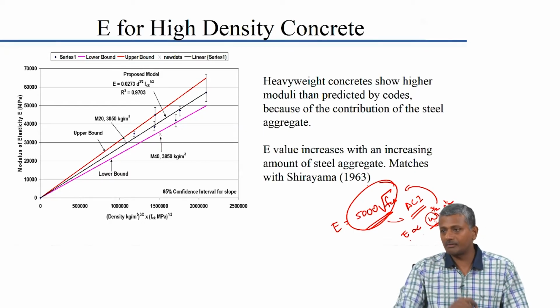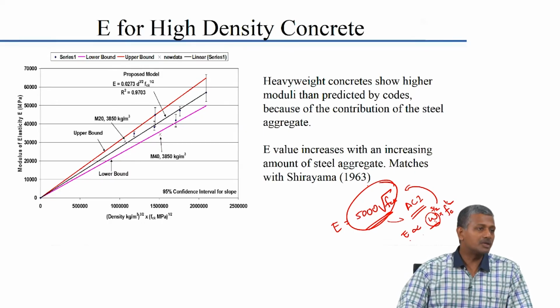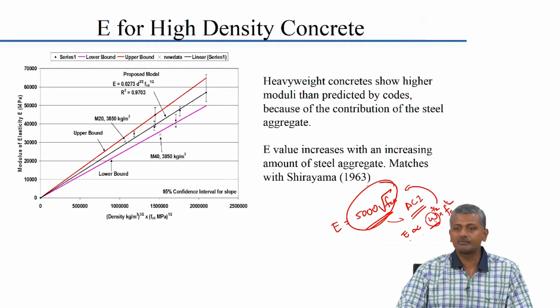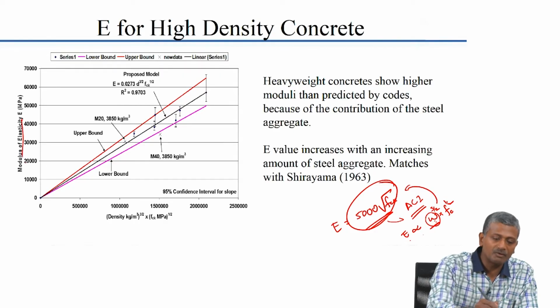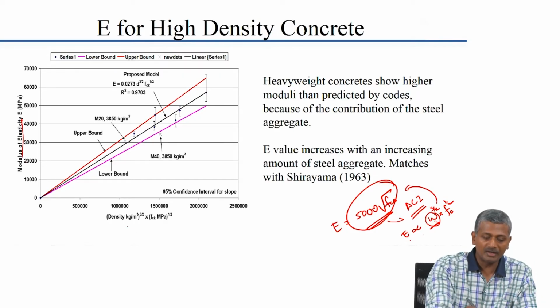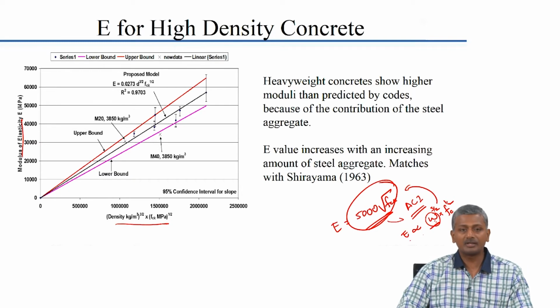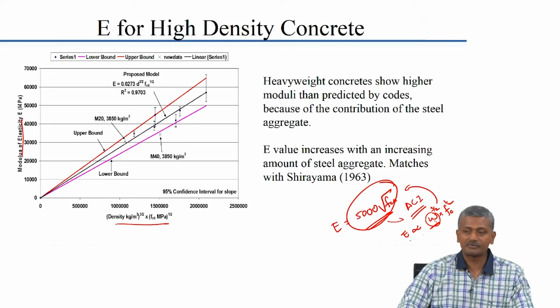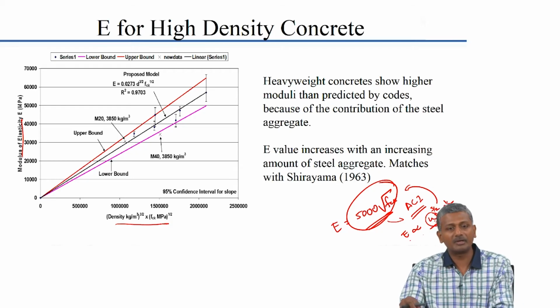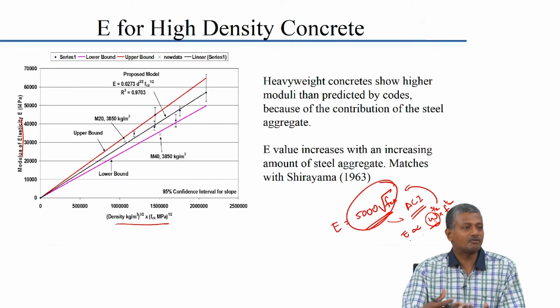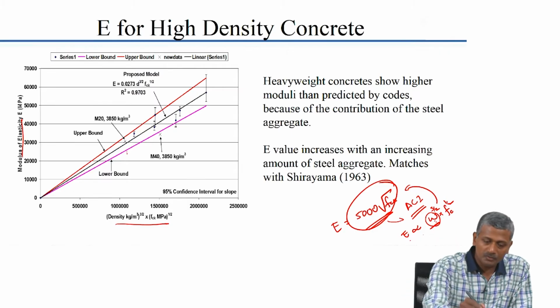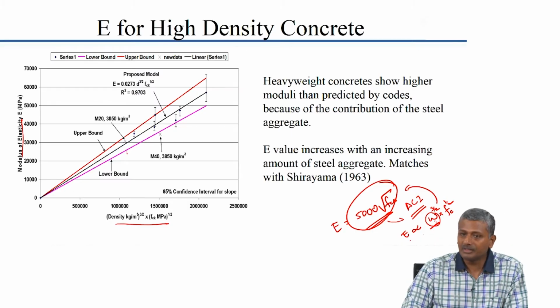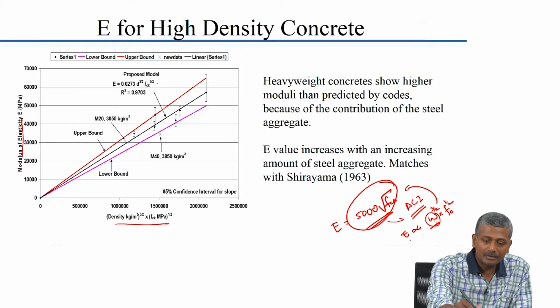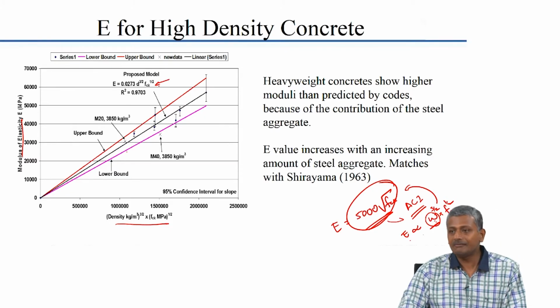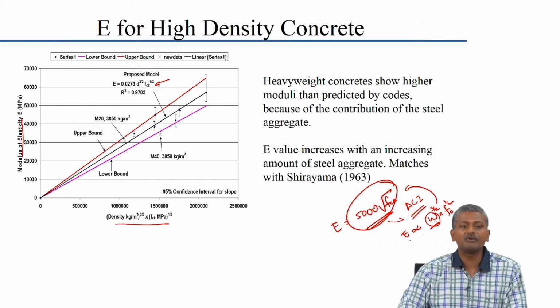So, we actually measured the moduli of elasticity using the equipment, but we found that the relationship was quite different from what was suggested for normal density concrete as per IS. So, we wanted to see what the relationship could be. We went back to the basics and plotted modulus of elasticity against the density to the power 3 by 2 multiplied by the square root of compressive strength. Again, there is nothing scientific or fundamental about it; it is a way of expressing the data, and indeed from this we were able to get a very good fit in terms of a straight line relationship, and a new model for estimation of the E value from the strength and density of heavyweight concretes was proposed.